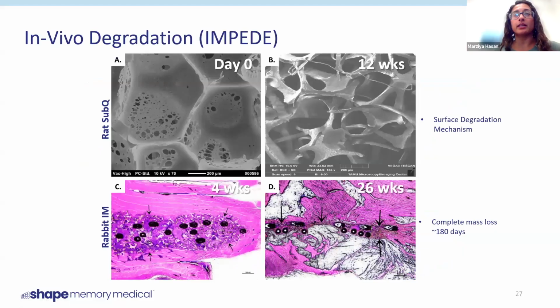These are just some animal studies we then did afterwards. On the top, we have a rat subcutaneous implant. You can see at day 0, the foam is maintaining good structural integrity. You can see the membranes, but at 12 weeks, it starts to look more skeletal. So something has been chewing away at the membranes, as we can tell from the SEM images. And what we learned from this is that our degradation mode is surface degradation. So macrophages or hydrogen peroxide is getting rid of the foam from the outside in rather than bulk degradation.